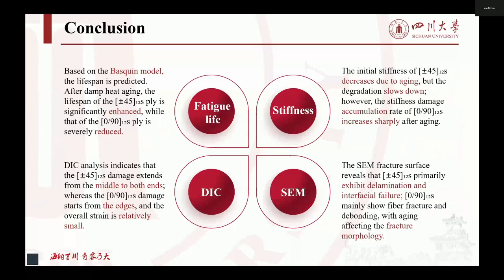Finally, conclusion. Through systematic experiments and rigorous analysis, I have found that after hygrothermal aging, the fatigue life of the 45-degree laminated board is significantly enhanced, while the fatigue life of the 90-degree laminated board is severely reduced. The damage of the 45-degree laminated board extends from the middle to both ends, while the damage of the 90-degree laminated board starts from the edge, and the overall strain is relatively small.